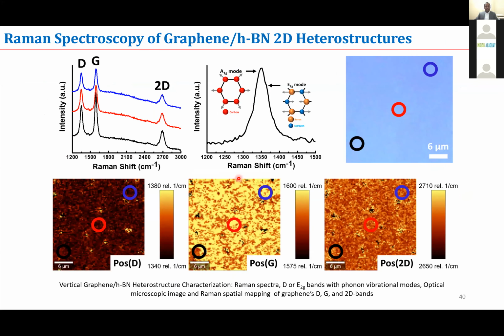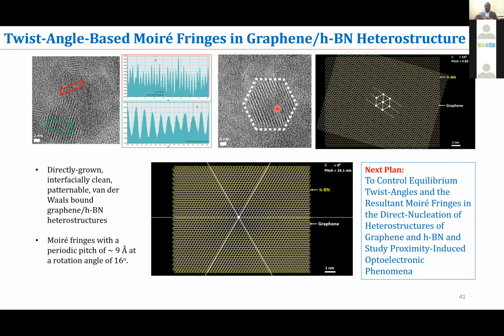And these are the Raman as well as optical characterizations of the heterostructure, graphene on boron nitride. Here you can see the D, G, and 2D Raman bands that correspond to graphene. And for boron nitride, the Raman band is at about 1365, which is very close to the Raman band for graphene's D band, which is the defect-induced band in graphene. So therefore, you can see here a shoulder that corresponds to boron nitride. So that means boron nitride and graphene are both formed here. They're continuous from this mapping, from the D, G, and 2D band Raman mapping of the structure. So these are continuously formed, and most importantly, these structures are rotated in situ.